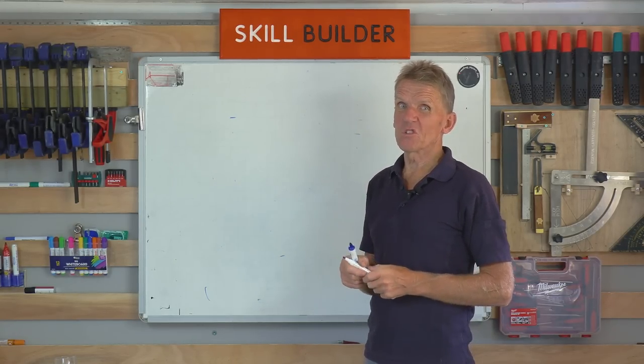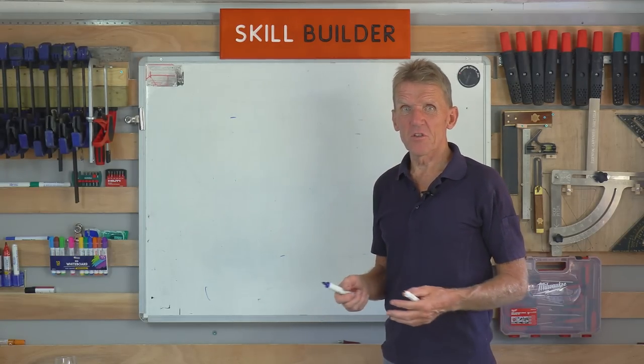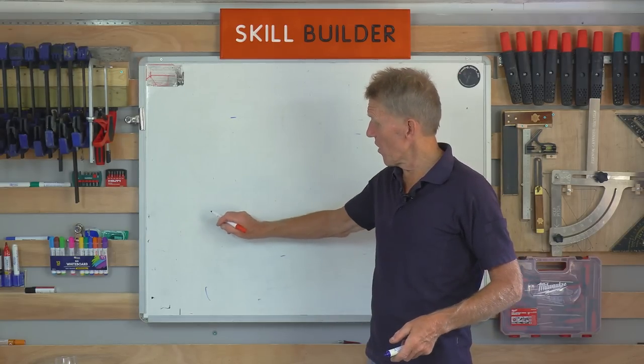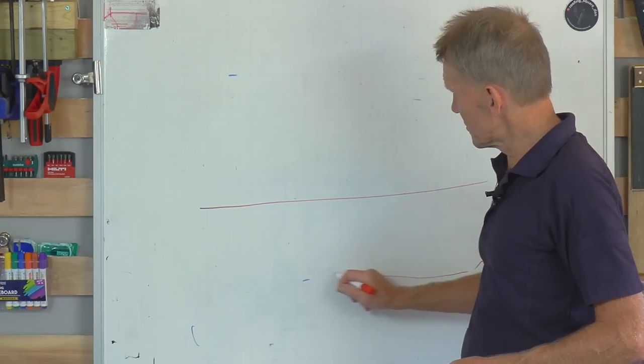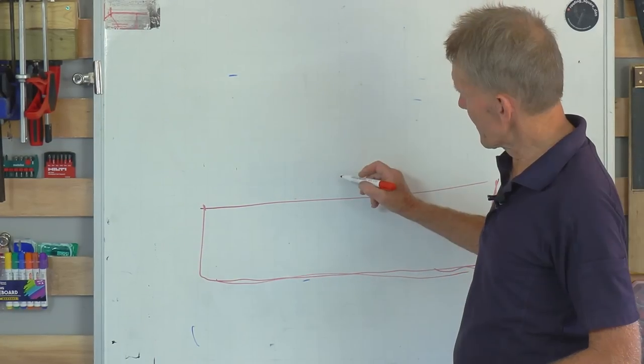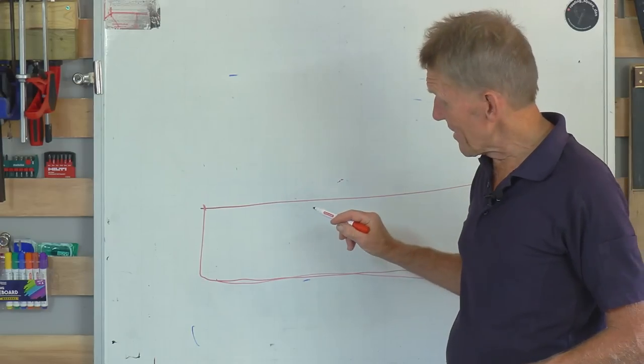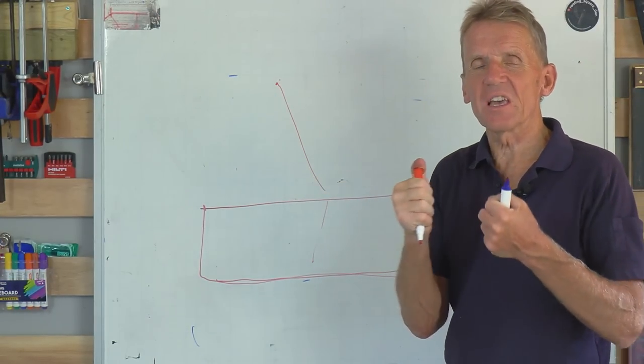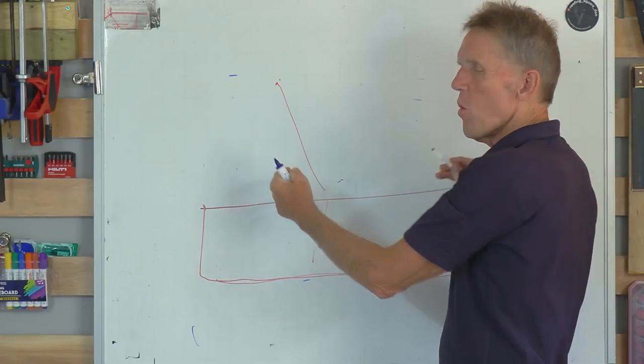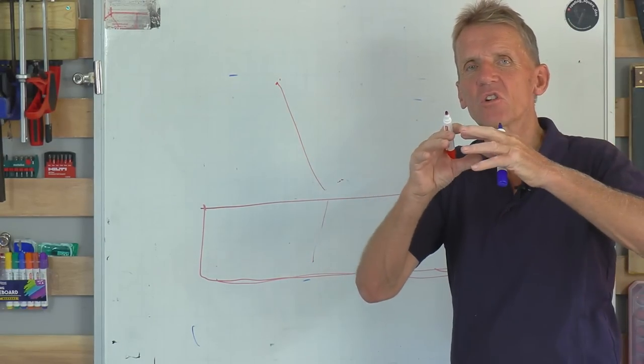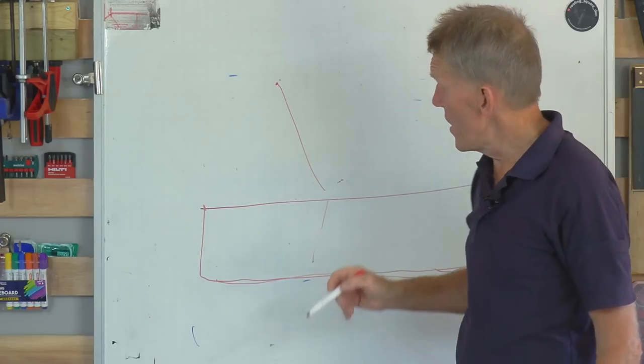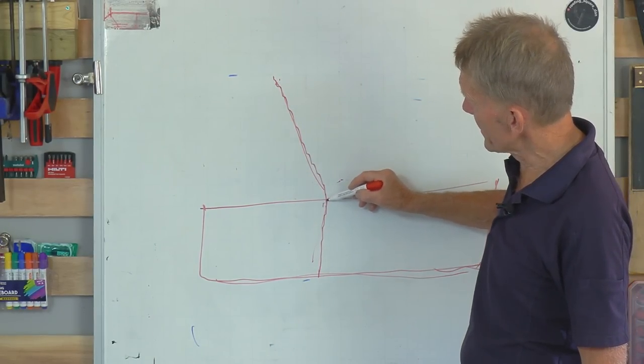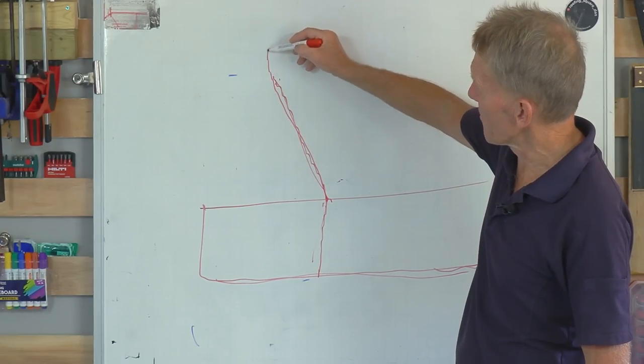Now, if you've got yourself a house that was built, say, from the 1930s onwards, and may have been built with sand and cement, and you've got a concrete foundation, nice deep concrete foundation, say three foot deep, the brickwork is built on top of that. And if that cracks, and the wall cracks above it, because it's not going to crack across the wall in the way that the sand and lime does, you're not going to spread that movement out over the whole wall, you may find that you get one large crack, all the way down through the foundation and up through the wall.